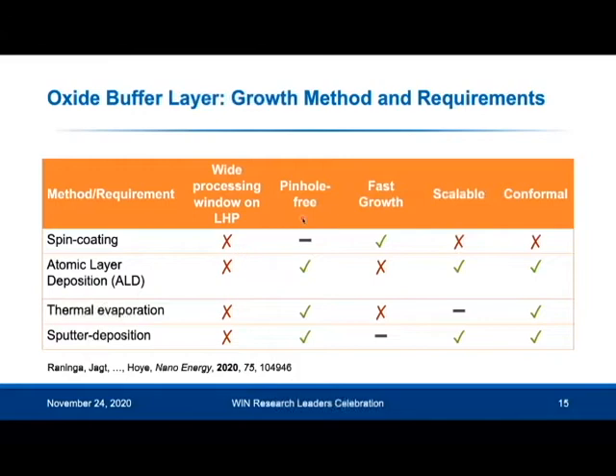But some of the other requirements for the oxide buffer layer include the fact that it has to be pinhole free, and the growth method needs to be fast and scalable, so you can use this on an industrial scale, and so that you make sure the top cell doesn't add too much to the costs of the bottom cell when you're making a tandem. And also the oxide needs to be conformal, because the most efficient perovskite silicon tandems are based off front textured silicon, and it's front textured to make sure you have minimal light reflection, so you get better light management. So you need to make sure that the oxide is also conformal to these micron-sized pyramids in your solar cell.